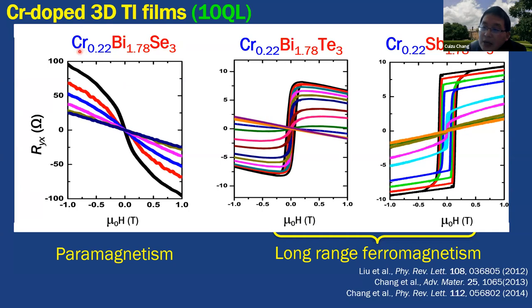We can say that chromium-doped bismuth selenide, chromium-doped bismuth telluride, and chromium-doped antimony telluride... We can see in chromium-doped bismuth selenide, there is no hysteresis. So this is just a paramagnet. It's not good. So we forget this kind of paramagnetic chromium-doped bismuth selenide for the realization of the quantum anomalous Hall effect.